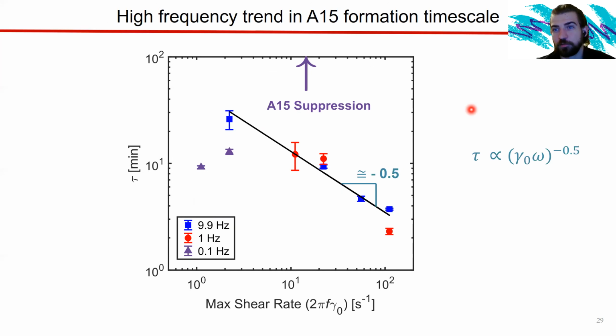I'm a chemical engineer, so we're going to try to normalize these. Now, when we plot the data against the maximum shear rate during oscillation, which is basically the frequency times the strain amplitude, we get this trend where the high frequency and intermediate frequency data roughly follow this empirical trend line with a slope of minus 0.5. However, the low frequency data do not follow this trend.